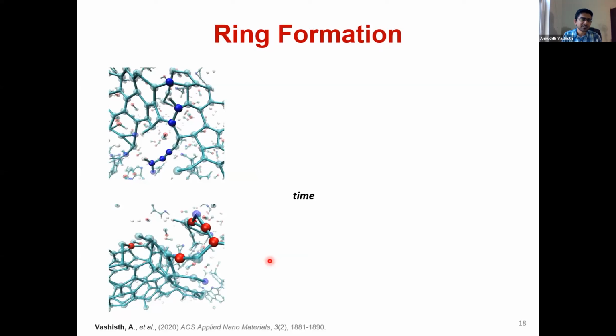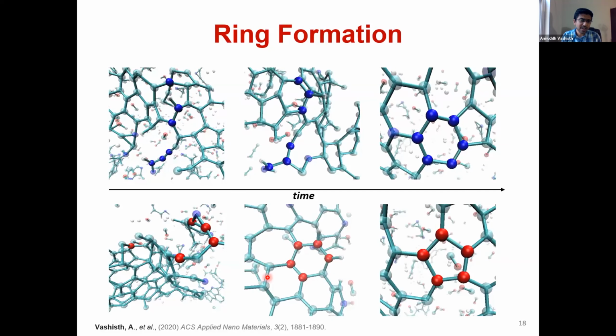Next, we looked at the snapshots. So we looked at the simulation process very carefully, very minutely. And what happens is that when you start lasing a polymer, it converts into an amorphous structure. And this amorphous structure finally converts into a very ordered structure. If you look at how exactly the ring formations are happening during the whole process, you can see that there are these 6 carbon atoms in the structure. They are kind of not all together during the amorphous phase, but once the ordered structure starts to form, you can see all these 6 carbon atoms getting together to make a 6-member ring.